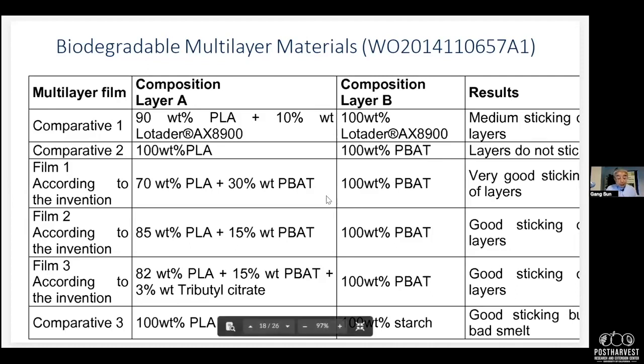Even more interesting is the look of it. There are some commercial products that are PLA, and also with starch. Okay, starch based, starch and the PLA, but remember the starch is very hydrophilic, and hydrophilic materials normally absorb a lot of moisture. So I think there would be some kind of indication that they use the starch layer to provide some kind of balance for the moisture for the packaging materials.